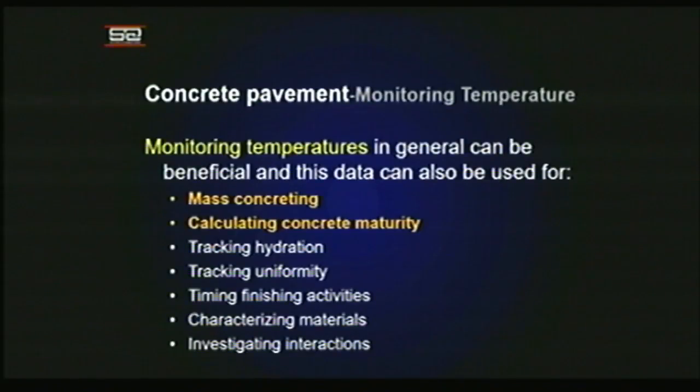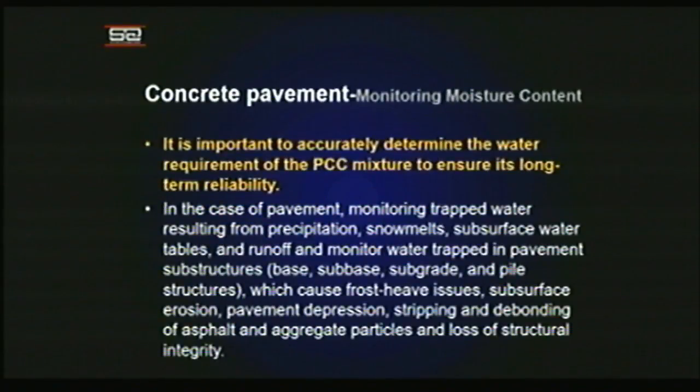And at present, when we are talking about concrete innovations, what is required is calculating the concrete maturity, which has been quite accepted worldwide. It is also based on standard procedures laid out in ASTM, as well as tracking of hydration, tracking uniformity, and timing finishing activities. These are the things that can be monitored using temperature sensors. When you are monitoring temperature, you also need the moisture content or relative humidity, because most of the curing takes place on the field using moisture, the water.